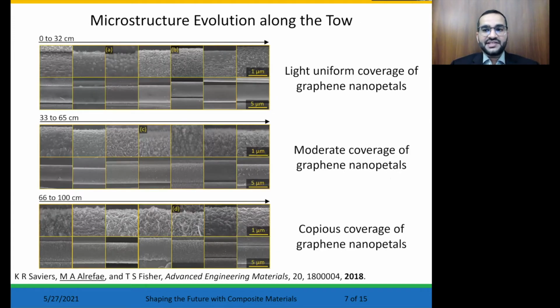The changes of electrical resistance and capacitance along the 1 meter sample can be correlated to the microscale structure of the segments, as shown in the SEM images here. Initially, light deposition of vertical graphene takes place, followed by moderate coverage of vertical graphene, and finally, in the second half, abundant deposition of vertical nanopetals occurs. The trends in SEM images explain the evolution of the electrical resistance and capacitance along the tow. The improved properties in the second half of the sample are due to the well-structured growth of vertical graphene.